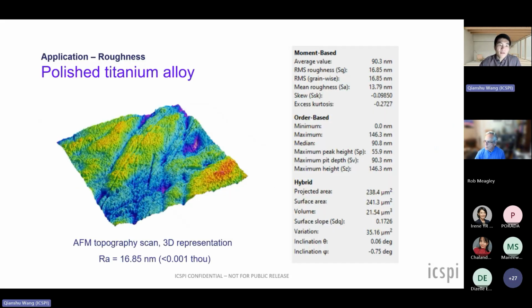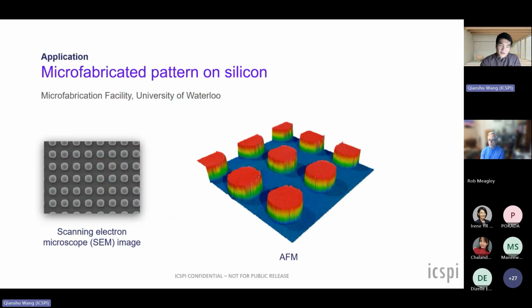This is an example of a polished titanium alloy. Here you can see a 3D representation of the topography on the left, and on the right, various statistical quantities that come out of AFM. The Ra roughness is approximately 16.85 nanometers. You also get the maximum and minimum pit depth and peak height, and information such as surface area. AFM allows you to get very powerful, very precise data that lets you further hone your processes. It's a really good tool for assessing the effect of processes on different materials and doing before and after comparisons.